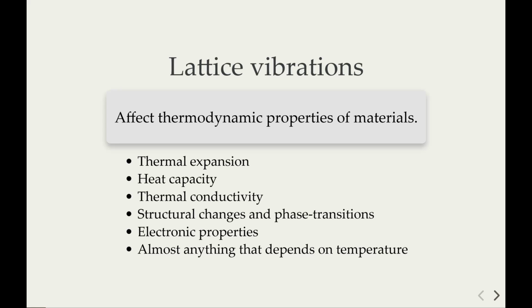The main reason is that most of the properties of solids depend on phonons, on lattice vibrations. The reason is quite simple: the energy excitation of phonons is comparable with room temperature. This means that when you change temperature by a bit, what actually happens in a solid is that you change the occupation number of the phonons, exciting them, and this excitation interacts with other excitations in the system, changing the thermodynamic properties.